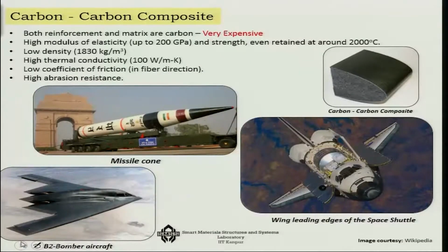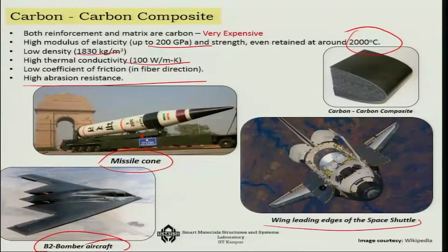Next is the carbon-carbon composites, where carbon is the fiber and carbon is the matrix. Here it's very expensive because the procedure by which we make it is also very expensive. It has a high modulus of elasticity up to 200 GPa and strength, and it can retain its properties even up to 2000 degrees centigrade, which is a very high temperature. Also it has a low density, high thermal conductivity, a low coefficient of friction, and high abrasion resistance. That is why it is used in missile cones, in B-2 bombers, in wing leading edges of the space shuttle. So wherever there is a very challenging environment, we apply these carbon-carbon composites.